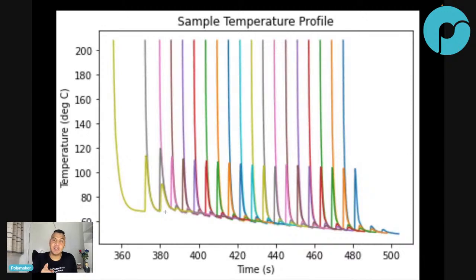However, it's going to improve your layer adhesion because you are going to print on top of a material that is already hot. And, sorry, I'm really sweating. Yeah, maybe we have to look more into this, because you are going to have a more uniform temperature because you print very fast. So that means you have a more homogeneous shrinkage. So shrinkage, not thermal shrinkage, right? Elastic shrinkage. So with that in mind, maybe it helped.